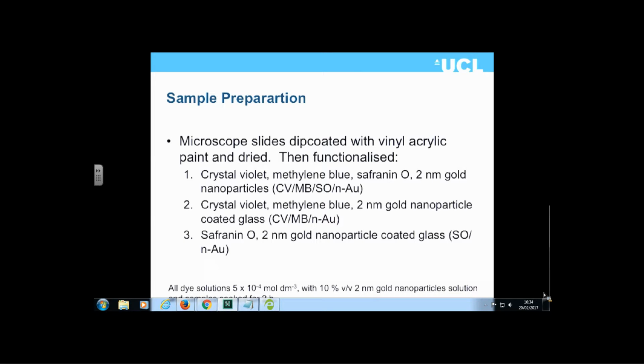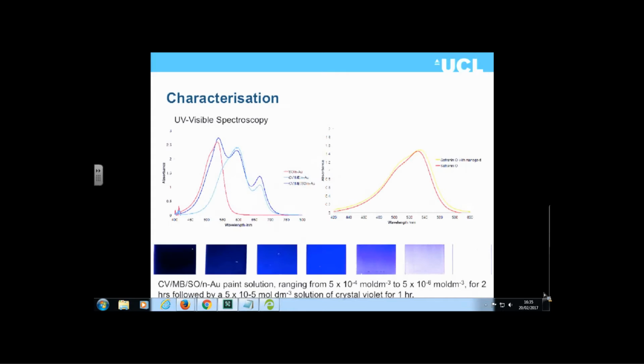And what we found is if we also incorporate nanoparticles—gold nanoparticles or zinc oxide nanoparticles—when the nanoparticles are present, they give a much higher lifetime for the excited state of the dye and better transference and generation of reactive oxygen species. So we end up with materials which are very, very potent at killing bacteria.